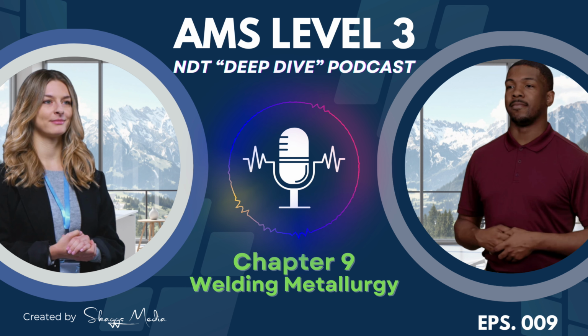Let's talk about heat input. That's something the inspector might actually calculate or verify on the job, right? There's a formula for it. Yes, absolutely. Heat input, usually measured in joules per inch or kilojoules per inch, is calculated from the welding parameters. The formula is heat input equals welding current, amps, times welding voltage, volts, times 60, divided by the welding travel speed in inches per minute. That times 60 is just to convert minutes in the travel speed to seconds, so the units work out correctly to joules. Okay. Amps times volts times 60 divided by inches per minute.